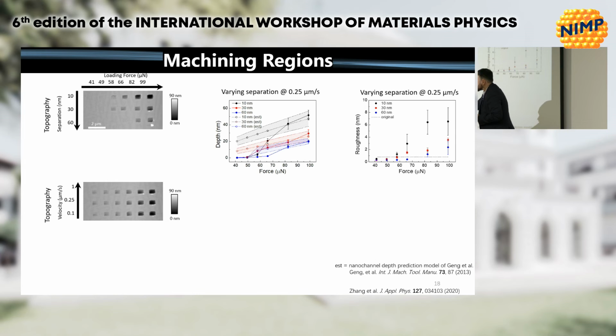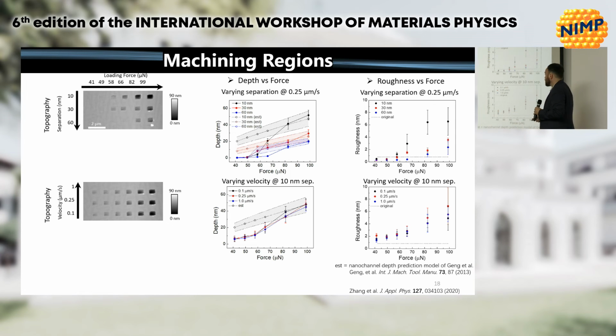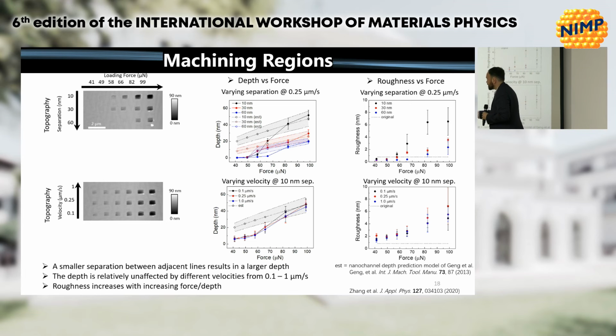And also we can do this experiment as a function of tip velocity, how fast the tip is moving for particular separations. So for the most part, we don't see a very strong tip velocity effect. Of course, the force is a very key parameter. The higher the force, the more you remove. And there are different regimes. So there's a plowing regime and kind of a polishing regime. Plowing, you're actually removing the material. Polishing would be more suitable for tomographic approaches where you don't want to damage the layer that you're trying to image the functional property of.